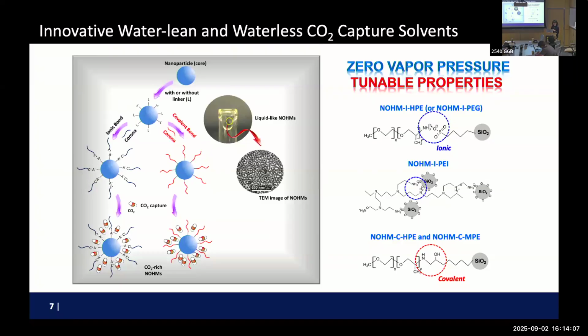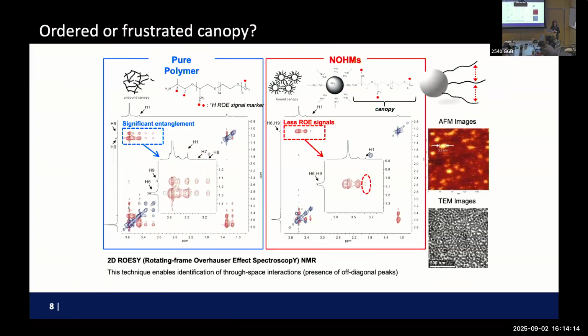So from there, we wanted to see whether it does change the structure of the polymer as you tether them. This is just a simple 2D NMR data. If you are not familiar, left and right, there's a very big difference between the signals, right? Because this is untethered polymer. This is after we make NOHMs by tethering them. Basically, what this signal is telling you is that the polymers I tethered onto the nanoparticle were stretched out from each other. So it's an indirect method showing that there's a lot more free volume we created.